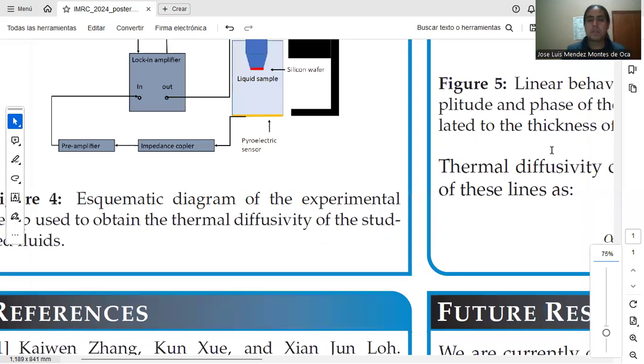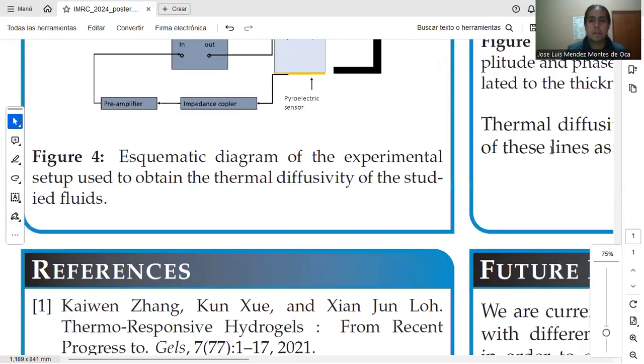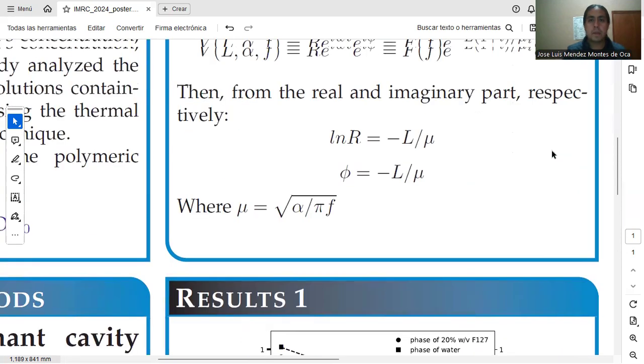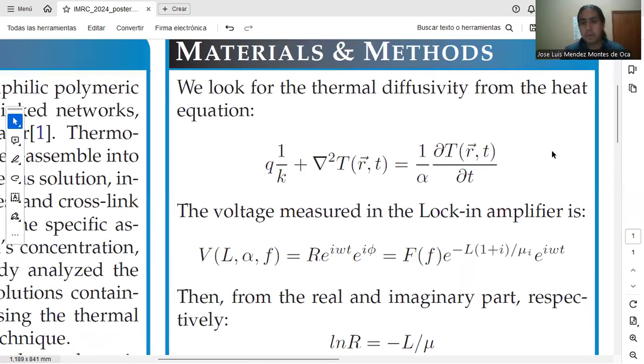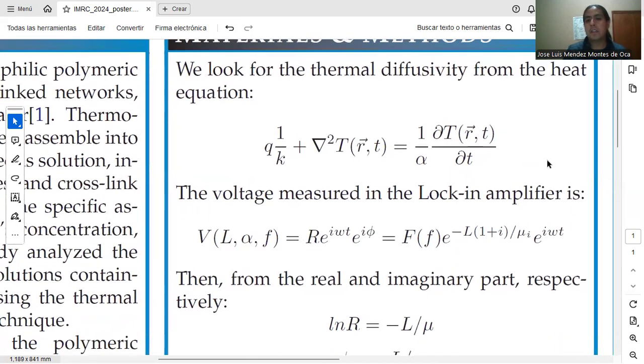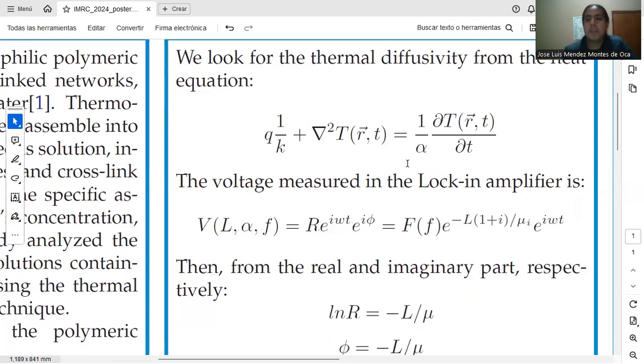And well, we use the heat equation, which says that if there is a change in the temperature at some point of the material or at some boundary, these changes are transported across the material in time and in space. And how efficient this transport is, is given by this parameter alpha, which is the thermal diffusivity. And we can solve this equation in one dimension.